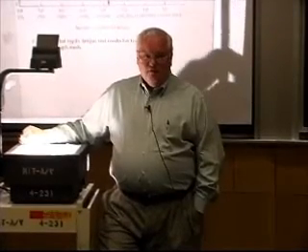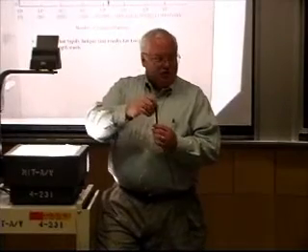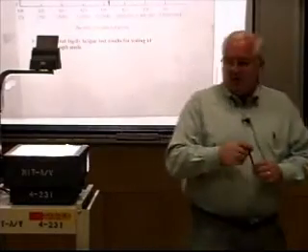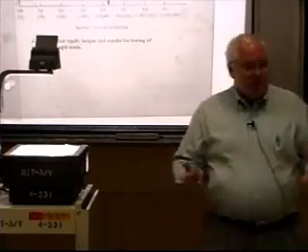There are people who've done 10 to the 8th cycles, and a very few samples where people have done 10 to the 9th, but that's when they're putting in a special machine and vibrating at 100 hertz or even 1,000 hertz. Well, you run into problems there in your testing because you can overheat the sample just because you're putting enough mechanical work in it that it can heat up. And so now you're not doing a room temperature test anymore. So you run into limits as you go through things.